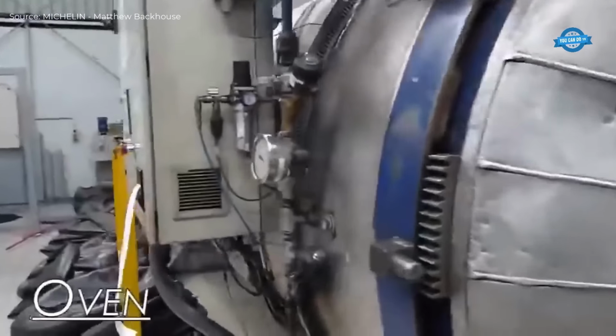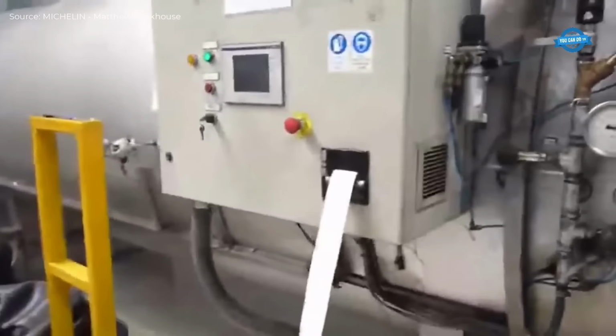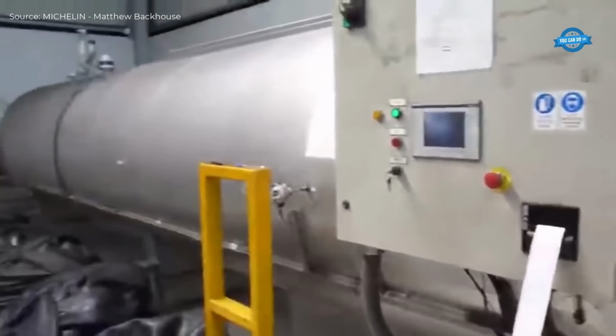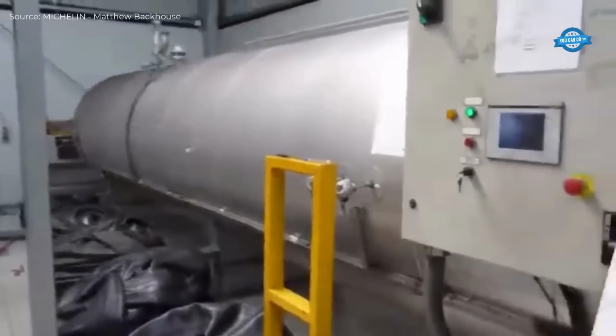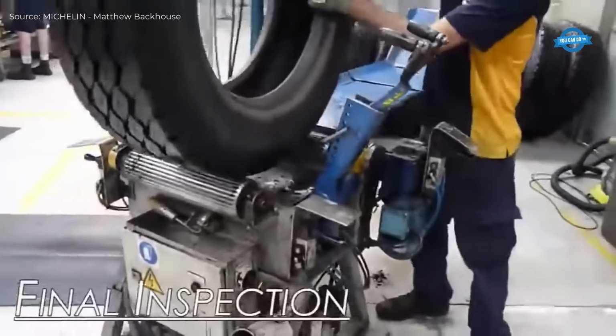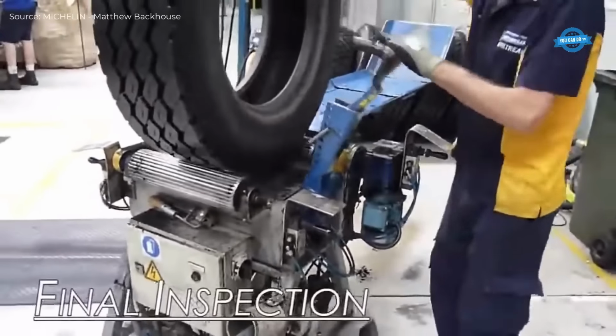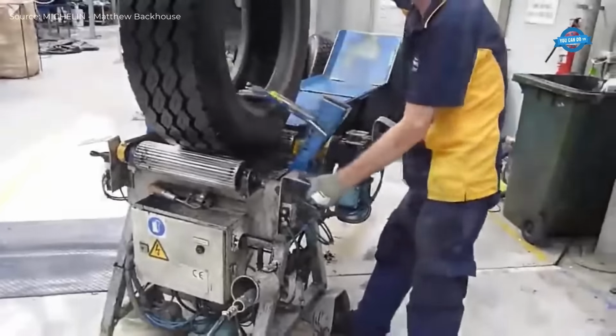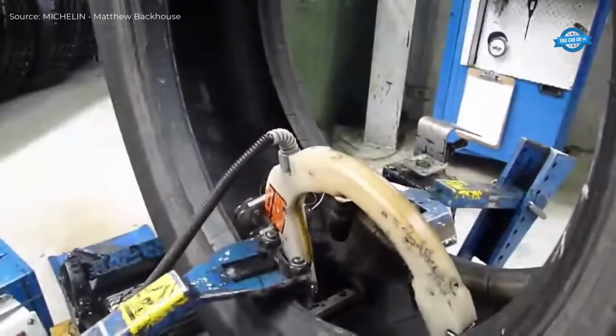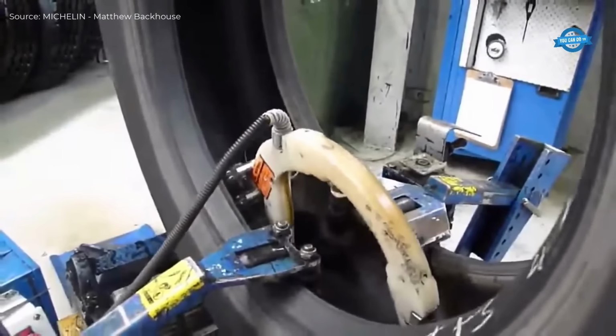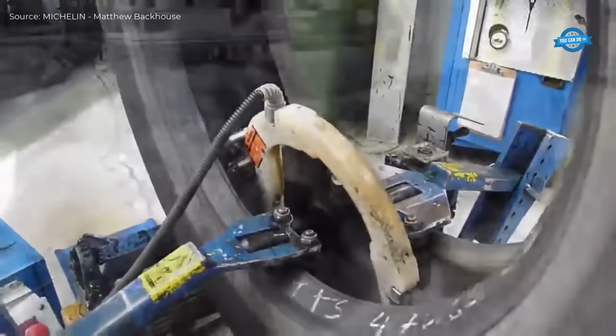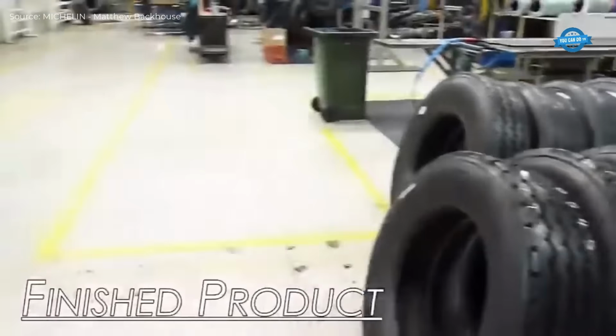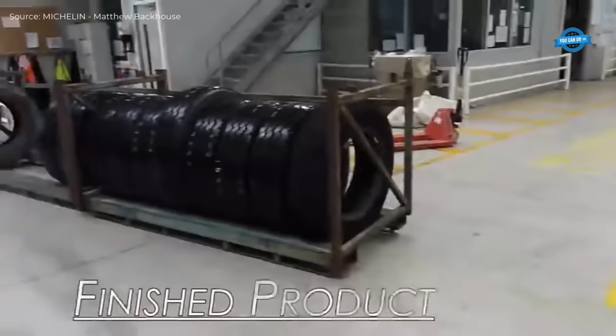The tire undergoes curing in an autoclave at approximately 100 to 110 degrees Celsius, 212 to 230 degrees Fahrenheit, for 3 to 4 hours under high pressure. This vulcanization process bonds the new tread permanently. Every retreaded tire undergoes a comprehensive inspection, including pressure testing and visual checks, ensuring safety and performance.